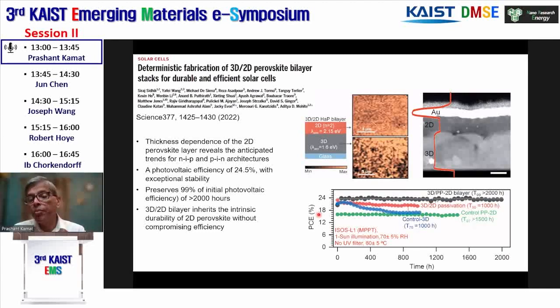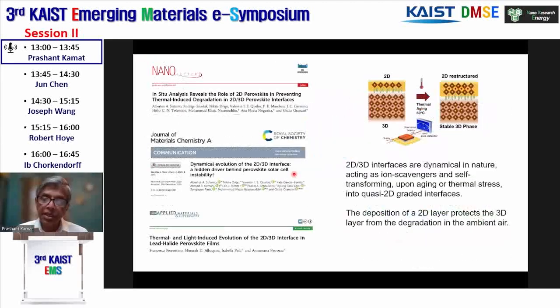And interestingly, if you read the literature on perovskite solar cells, there has been a lot of push to deposit a 2D layer on a 3D layer. And everyone sees, as you can see here, very stable performance for 2,000 hours. They also show how nicely they can lay down this 2D layer on a 3D. So again, there are several papers claiming this, and the question that arises is how stable is this 2D layer? Is it the 2D layer, or is it the organic cations that are causing this, or a quasi-2D phase? That is a debatable question.